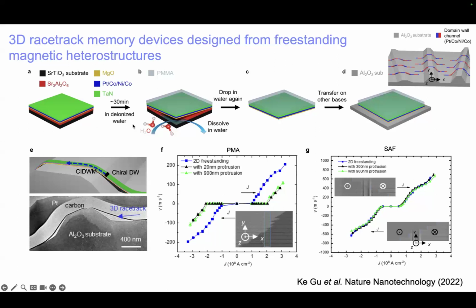And on top of this, we make a racetrack using first magnesium oxide and then this platinum cobalt nickel cobalt structure. And then what Kei does, he dissolves the strontium-3 aluminum-2 oxide-6 layer in water on a 1 centimeter by 1 centimeter substrate. And then he floats off the racetrack on top of the water, and then we can transfer it onto something else. And what we do is we pre-prepare a sapphire wafer, in which in the top right, you can see we made these little hillocks, and we make the racetrack to basically cover this hillock. And this can be seen on the bottom left in E.